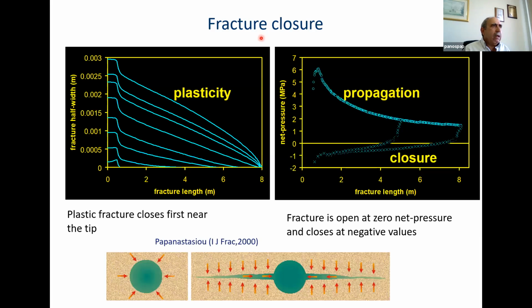Now I will look at the fracture closure. So again, with the plasticity solution, we propagated the fracture, and it reached that fracture profile, which I show here. You can see the last line. And then I will allow the fracture to close down. And this is the fracture profile. As the fracture closes, you can see that it closes quite a lot. It almost covers half of the volume without changing the fracture length. And then the fracture closes like in a zip pattern. It closes first near the tip, and then the closure lasts near the wellbore.